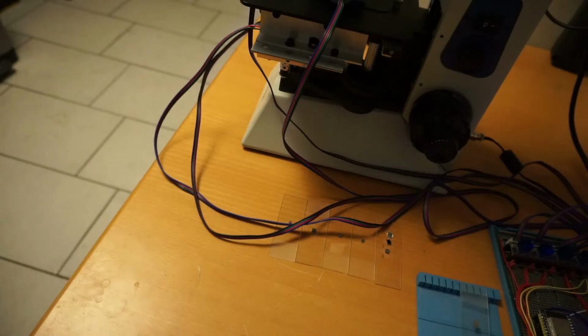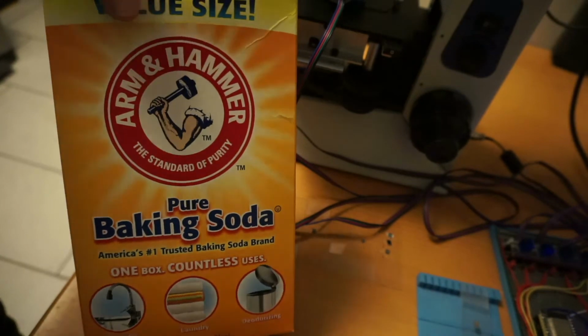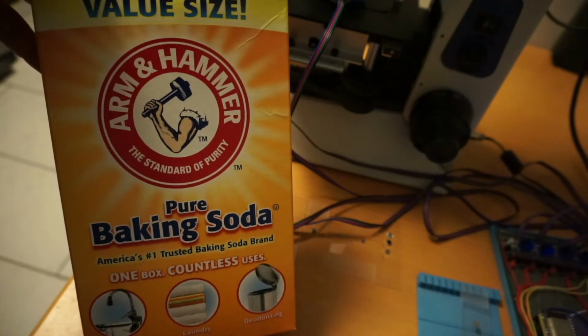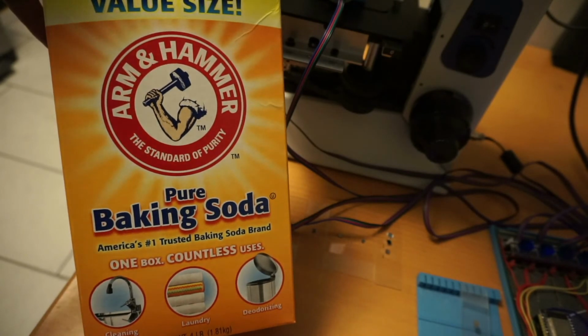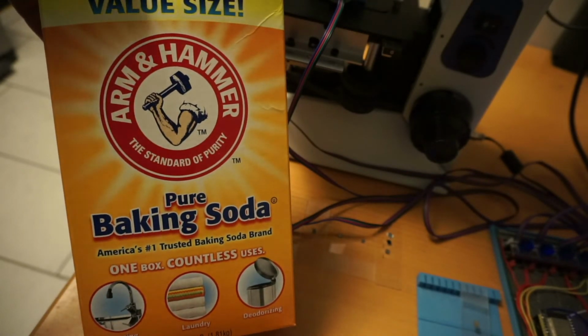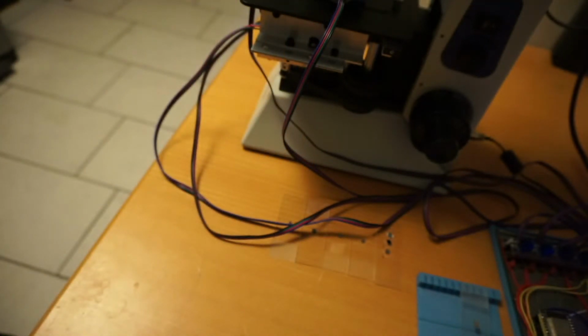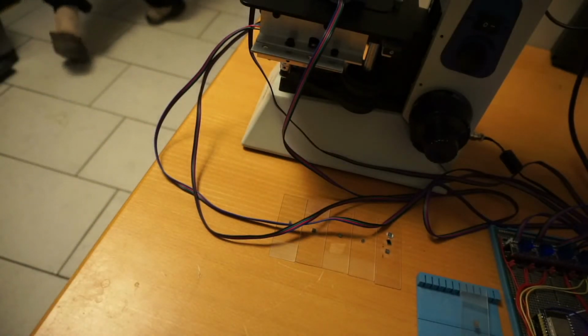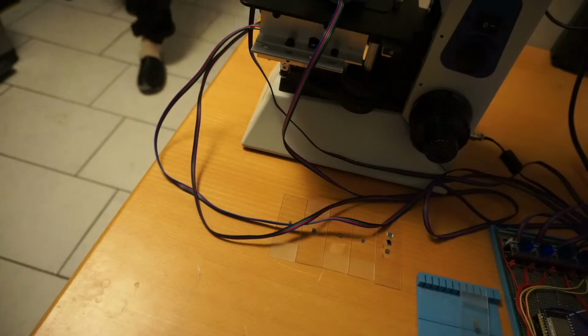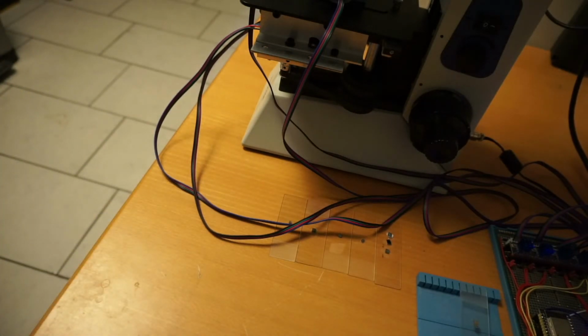Hydrofluoric acid, I tend to wash it off with acetone, which is also not a very nice liquid. Dilute it quite a bit in acetone, and then I use the chemist's happy Mr. Baking Soda, which is an alkaline, so it helps really just neutralize most of the acidity. I haven't looked into the exact chemicals, but it seems to be working fine for me at least. I probably should look that up.